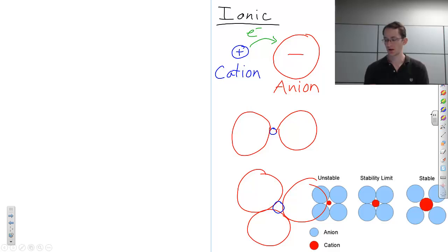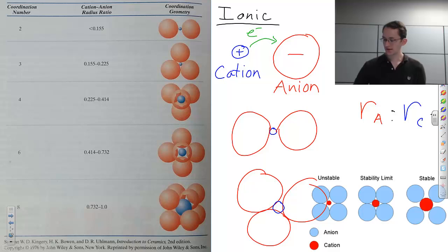And this figure you can find in your book, it tells you the relative stability of the different radii of cation to anion ratios. And so if we are able to take the radius of the anion and compare it to the radius of the cation, we'll be able to determine how many anions we can fit around a cation. And the way we do this is called the cation anion radius ratio. So it would be RC divided by RA.